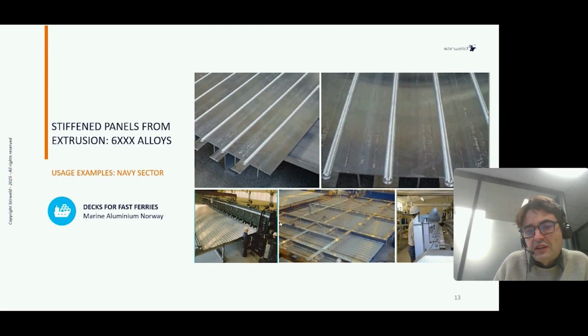And here I like this example because we can see one tip: how to remove the exit hole here at the end of the weld. So the application is Marine Aluminium Norway, and they add this run out tab. So as you can see, it's an external part placed into the jig, and so we complete the weld into this run out tab, and we cut this run out after welding. And so this is very smart because we save material from extrusion just by adding an external piece of aluminium, and we can easily cut this run out after.